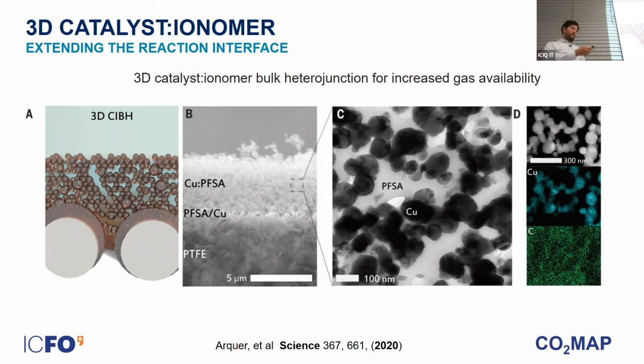So only within a very particular narrow window can you achieve high performance. And you are right, even in this case, most likely there will be a high fraction of copper nanoparticles which will not be connected, but most likely these will be oxidized and dissolved. We still don't know, because it's very difficult to characterize these materials during reaction.